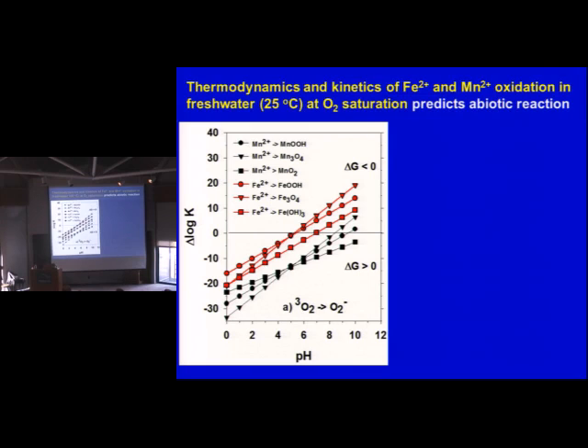In this case, what we did is we took manganese 2 going to these different species of solids, iron 2 going to these, but we looked at only oxygen in the first electron transfer step going to superoxide, a reactive oxygen species. And what you'll notice is that above this line is thermodynamically favorable, and below it's not. So this is just a pE-pH type calculation. And what you'll notice here is that at about a pH of 6, you still have the possibility of iron oxidation. But what about the manganese?